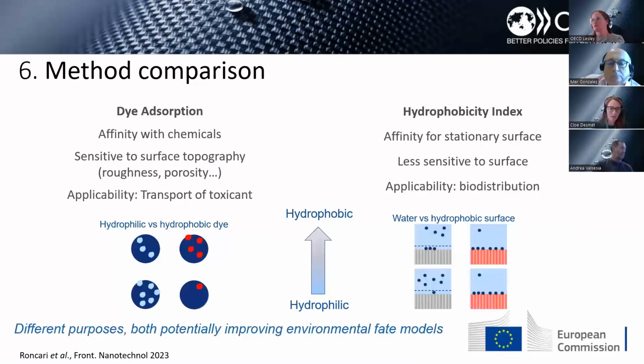As my colleague presented earlier, the dye adsorption method is simple since it's based on the interaction of chemical dyes with the nanomaterials, but this method has important drawbacks. Both methods, dye adsorption and hydrophobicity index, are based on affinity of the nanomaterials — in one case with chemicals, and in the other, affinity for stationary surfaces. With chemicals, there is a very high influence of surface topography, while the hydrophobicity index is much less sensitive to that, simply due to the size difference, as represented in the figure, with small chemicals binding on bigger particles in one case.